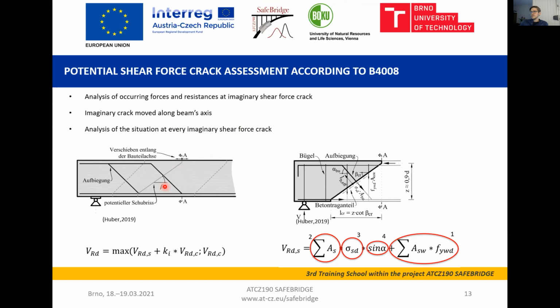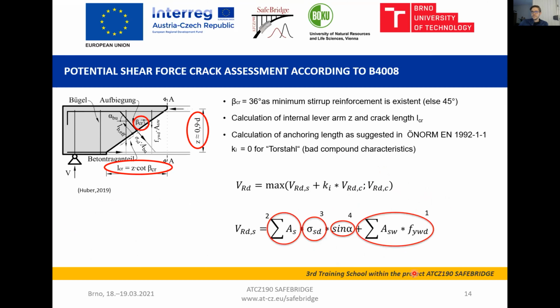This model is based on the model of the potential shear force crack. In this approach, the structure is divided by shear cracks, and the vertical forces are calculated along this potential shear crack, here you can see the edge of the shear crack. This potential shear crack is moved along the beam, from step to step to step. Some assumptions were made: the critical angle with minimum stirrup reinforcement was 36 degrees. If there's no minimum stirrup reinforcement, you have to take 45 degrees.